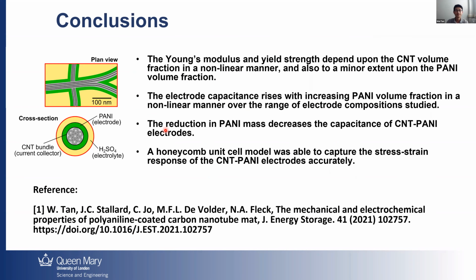So in conclusion, in our study, we found that the Young's modulus and yield strength, essentially the mechanical properties, depend on the CNT volume fractions in a nonlinear manner. And also, to a minor extent, upon the PANI volume fractions. The electrode capacitance, in contrast, rises with the increase of PANI volume fraction over the range of the electrode compositions. The reduction in PANI mass from our pre-charging effect actually decreased the capacitance of the CNT-PANI electrode. The honeycomb unit cell model is actually very capable of capturing the stress-strain response of the CNT-PANI electrode accurately.